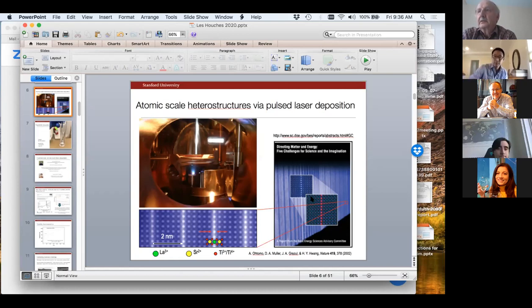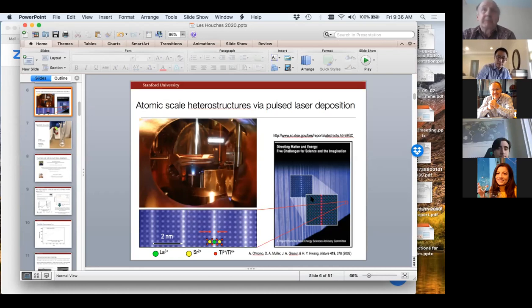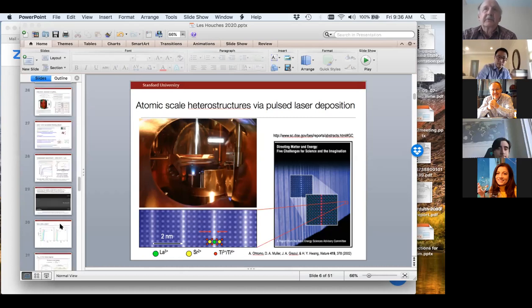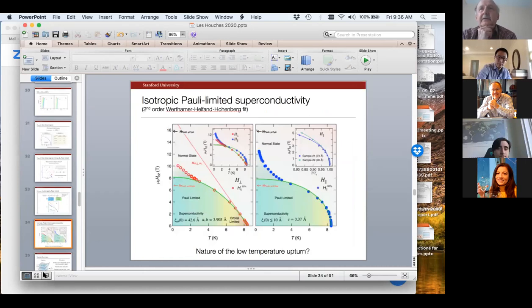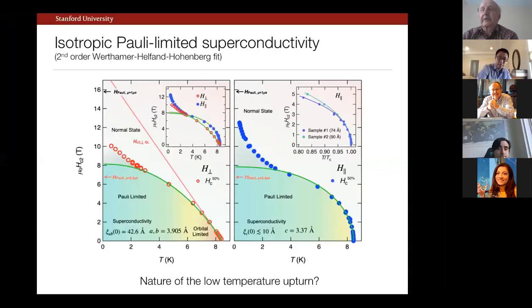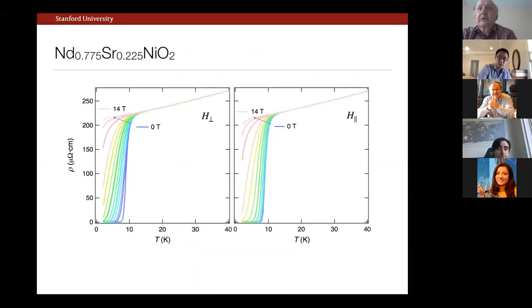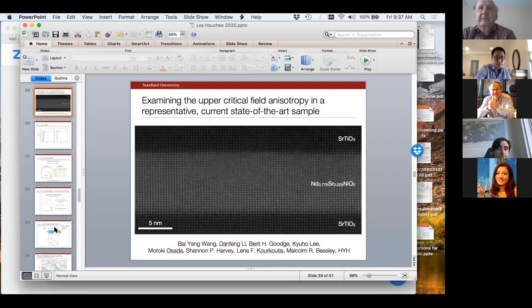Other questions? Well, okay, I'll shoot since I had two. You can measure in a magnetic field, which is either applied parallel or perpendicular to the film. And so going back to the comment that you were making on the slight upturn in the resistivity at low temperature, and you were exploring scenarios: if it were Kondo, you could tell in some sense by the magnetoresistance, it would be more or less isotropic.